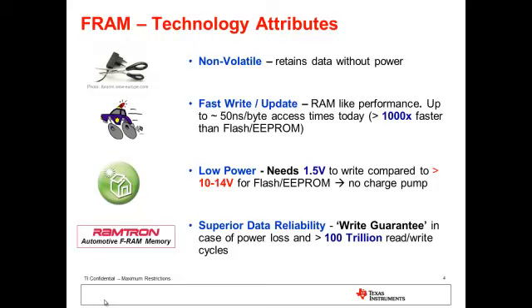So, why is FRAM non-volatile? This is because of the special dielectric material used in the storage capacitor — a ceramic that allows making use of the so-called ferroelectric effect. The term ferroelectric does not mean that the memory contains iron, the chemical element Fe, nor does it imply that the memory can be influenced by magnetic fields. In fact, FRAM is immune to magnetic fields. The term results from the hysteresis loop being similar to a magnetic hysteresis loop, which in FRAM results from an electric dipole formed by zirconium and oxygen atoms in the ceramic lead zirconate titanate crystal, PZT, used to implement FRAM.